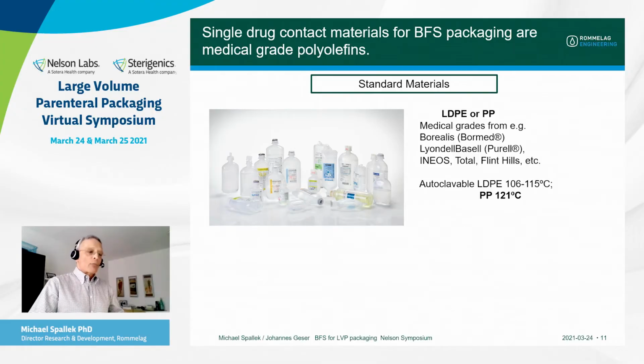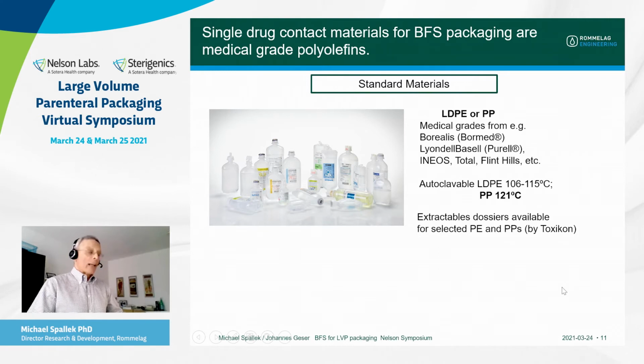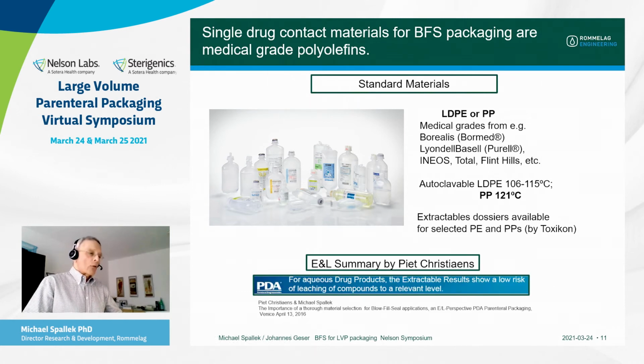We are in a Nelson Lab symposium. That's why you have to deal with extractables as well. So we did so. Together we worked out extractable dossiers for some of our most used polyethylenes and polypropylenes, former times with Toxikon, now with Nelson Labs. And here is a summary from Piet Christiaens from our conference, PDA conference 2016. One line summary for aqueous drug products, the extractable results show a low risk of leaching of components to a relevant level. That means that extractables and thereby leachables do not play a high risky role when using blow fill and seal packaging.